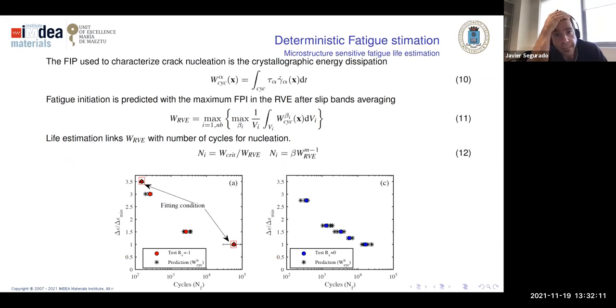We're focusing on the dissipated energy, while other people focus on the stored energy. The idea is to take the dissipated energy per cycle, go to each point, and see which is the energy dissipated on each slip system. So this is a map, because it depends on the point. From this map, we can then integrate in small bands that are parallel to the slip systems for every grain and obtain the maximum of this integral in all the bands of the RVE. That is the representative fatigue indicator parameter for the whole RVE.